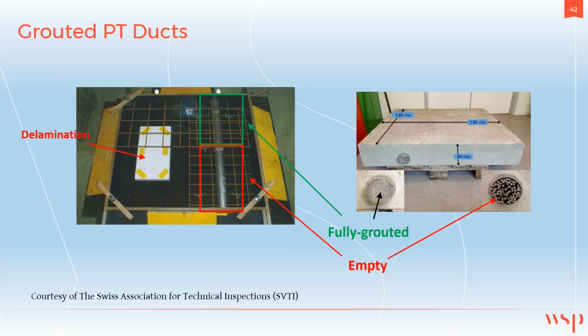We can use different NDE methods to see if post-tension ducts are fully grouted or not. For example, impact echo is quite effective. This example here shows a laboratory specimen which has a steel duct, and only half of it is fully grouted. So this half is grouted. And the slab also has an artificial delamination here on the left.